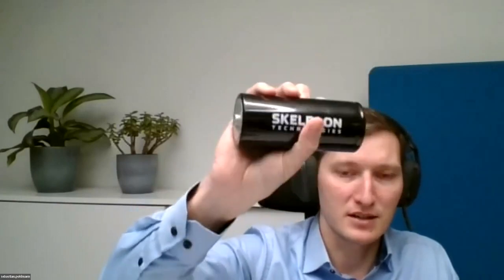Sure. So the one thing is that you can, of course, treat it just from the material standpoint and look at, okay, how many active sites can I have? What will this do to the lifetime? The important thing is that every supercapacitor manufacturer will evaluate the material not by its oxygen content or nitrogen content or whatever, but by its performance in the device, and normally in an industrial device. So whatever data you have on the small lab cells, it's always good to give an indication, but the real proof always happens in the large devices. So these are these very big cells here, which are made.